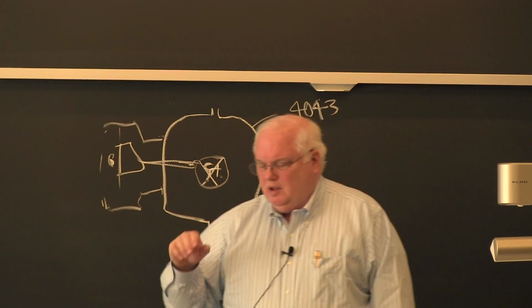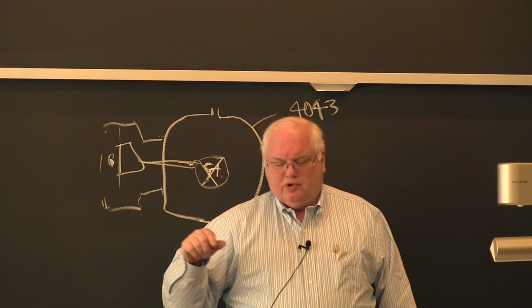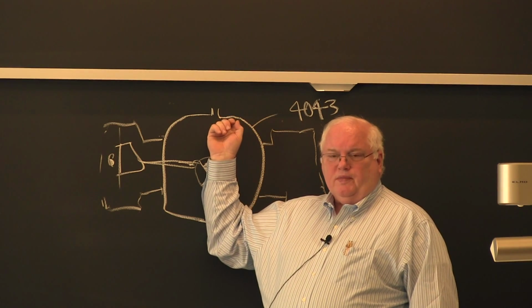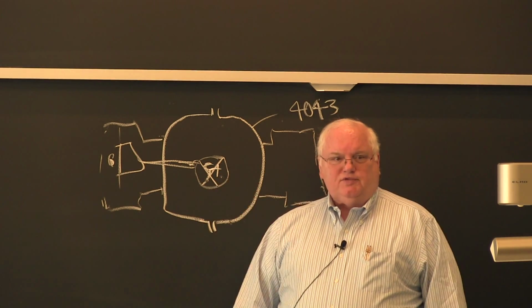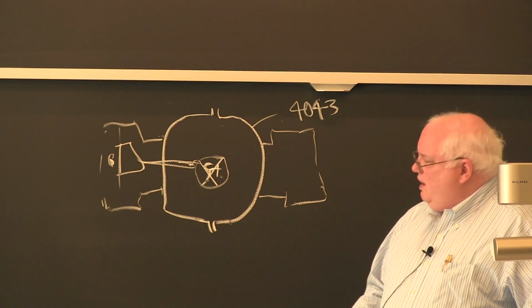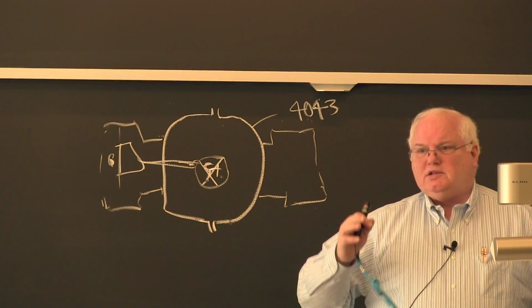And I just worked with them on an accident that occurred in Canada, and the Canadian Transportation Safety Board, similar to our National Transportation Safety Board, had investigated the accident, and they said, oh, your filler metal is softer than your base metal, and therefore you have undermatching weld metal, and that's the cause of this fatigue crack. Well, I had to help them respond to that, but in any case, for 30 years, every now and then, someone would go investigate one of these things and find out their weld metal was softer than their base metal, and they say, oh, that's the cause.